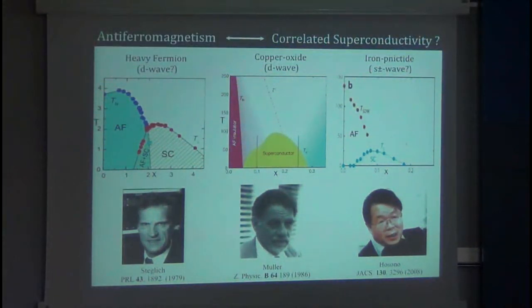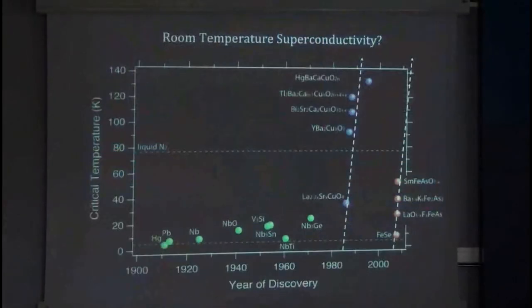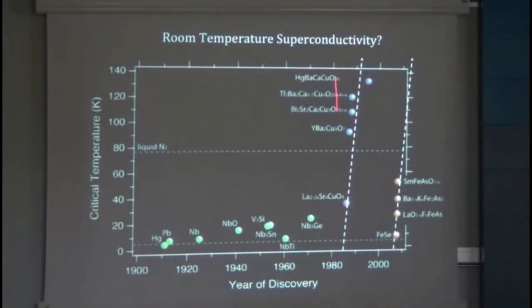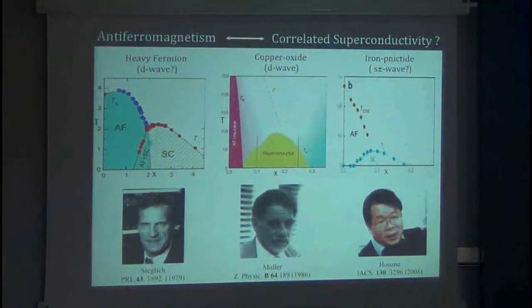Now, here is the question we face. It's clear for many reasons that whatever is making these robust Cooper pairs here cannot be the electron lattice interaction. It's got to be some other interaction which is strong enough to make Cooper pairs which can remain bound, let's say, at room temperature or above. One quantum mechanical phenomenon which survives well above room temperature is, of course, magnetism. And there's an a priori reason to suspect that antiferromagnetism is the key to this correlated high temperature superconductivity.